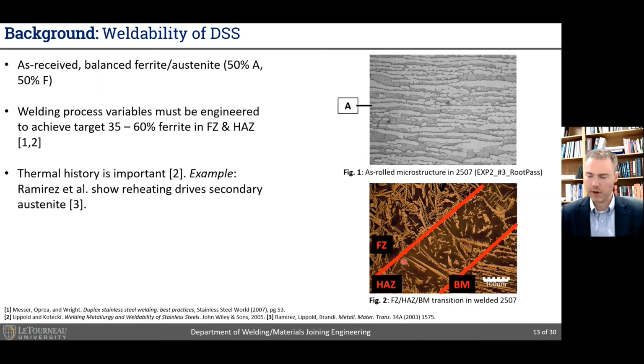As we look at a representative micrograph from our work, you can see that at this boundary between the fusion zone, heat affected zone, and base metal, we can see profound changes in the microstructure. The base metal is distinguished by this wrought, rolled type microstructure. In this particular alloy, the 2507, because of the suppression of complete transformation to ferrite, the heat affected zone actually tends to be quite narrow, which is beneficial. And then you can see the presence of austenite, which etches in the lighter phase here in the fusion zone.